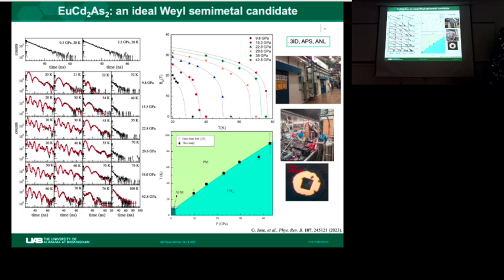look at the forward Mossbauer scattering signal, and in this case, you see here you have a whole bunch of oscillations, and by modeling these oscillations, you can get a sense of, let's say, the electric field gradient, the quadrupole splitting, and also the hyperfine magnetic field. And the hyperfine magnetic field reflects the strength of the interaction of the magnetic ions, and also when you have a spectrum like this, when there are no quantum oscillations, you know that these europium ions are in the paramagnetic state. So this basically tells you a lot of information about, again, the electronic environment and also the magnetic ordering temperature.